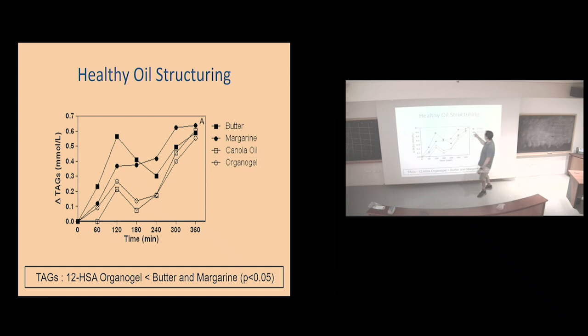And so what we do is we feed them butter, margarine, canola oil, or the organogel of the canola oil, and we didn't find anything. The only thing it did is that it behaves like the oil. Look at those two squares. That's the oleogel and the canola oil versus the difference in triglycerides that you would get from butter or margarine. And the butter's the one that raises your triglycerides. That's a marker of your health. Maybe you go to the doctor, they make a blood test and say your triglycerides are 100 milligrams per deciliter. It didn't change C-reactive protein. It didn't change HDL, LDL, all the lipoproteins, but it did change how much of the triglyceride was showing up in your blood. So it's gelled, but it behaves like oil. At least that's one thing that saved the whole study. We were thinking it was going to be a massive thing, but whatever.